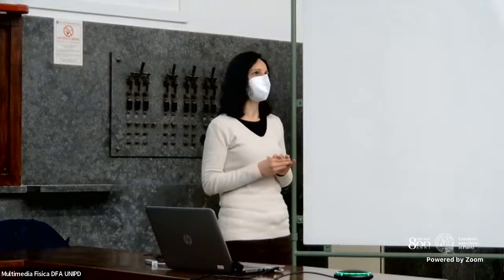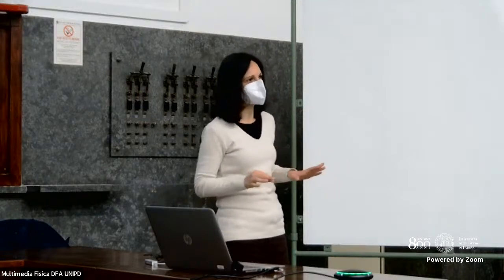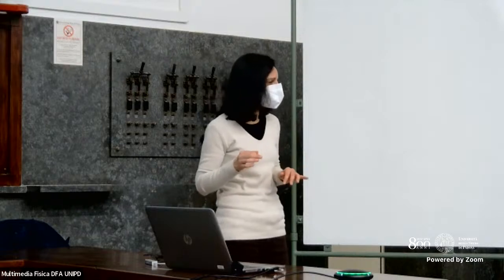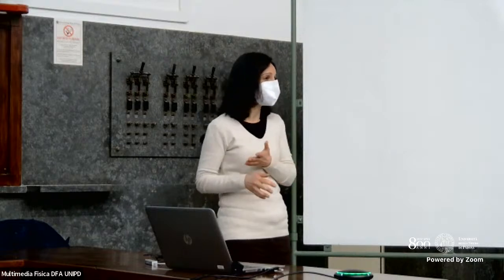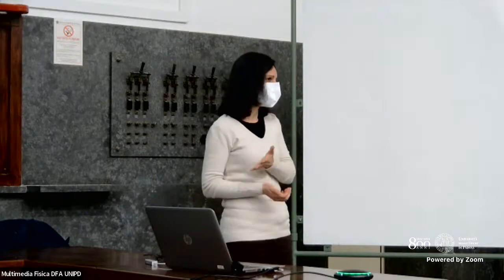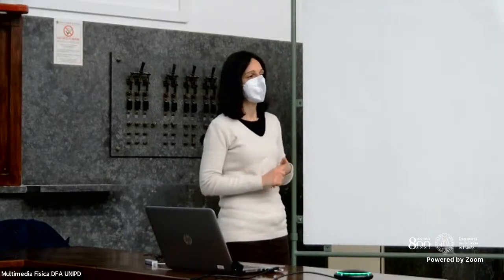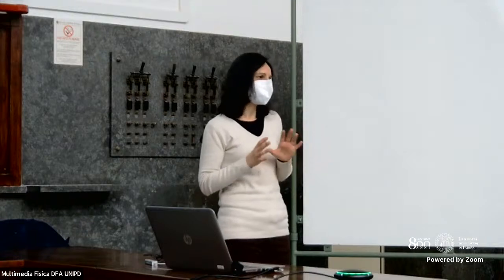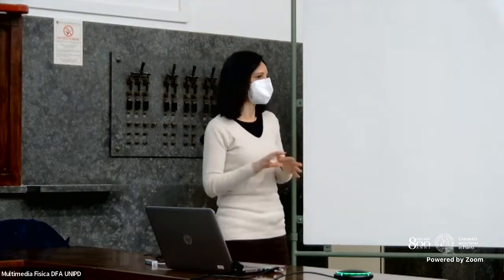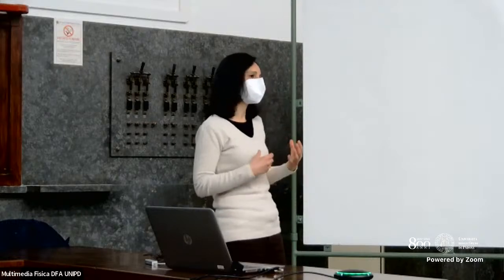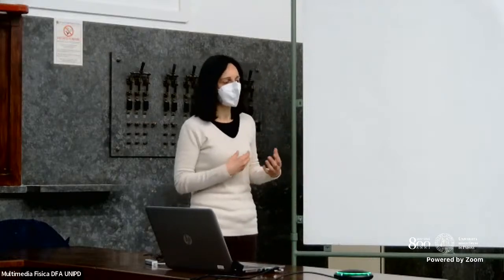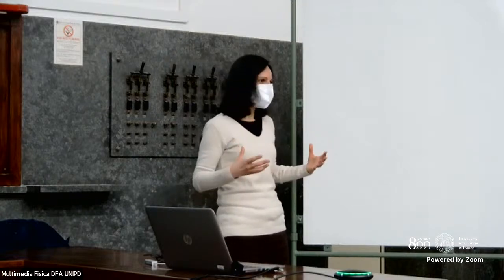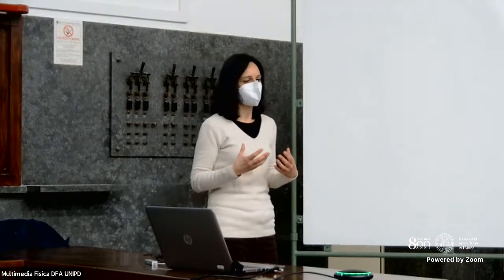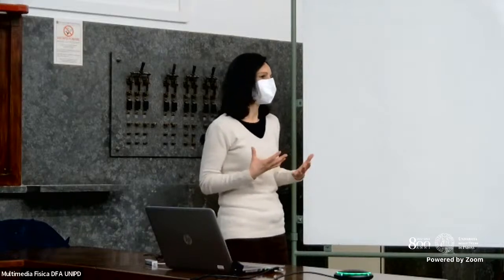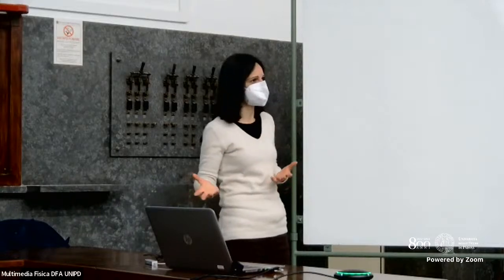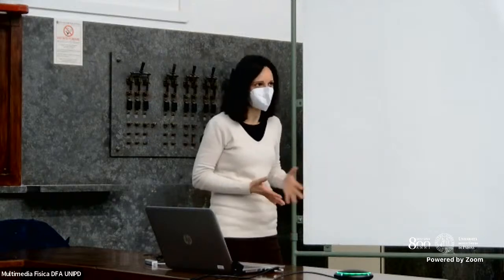But so far, the state of the art does not exceed 33 as a coefficient, while in the case of PZT, you have 300 and more. But the applications are much more limited in the case of PZT with respect to polymers. So, of course, in any case, you need to make a balance between several factors. Maybe high piezoelectric coefficients are not necessary for certain typologies of applications, such as the ones that I mentioned before.